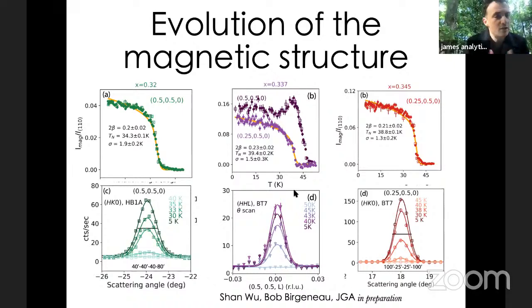And we've done some extensive DFT calculations with Jeff Neaton's group and Sophie Weber, where we showed that the stripe order and the zigzag order are actually very, very close in energy. And in fact, it's only a difference in the next nearest neighbor interaction that actually allows the system to switch from having stripe order as the preferred state to having zigzag order as the preferred state. So we think that's probably a natural explanation for why the switching turns off for the stoichiometric compound, and also why it has the opposite signs for the endpoints, for the underintercalated and the overintercalated. What's still remaining is the microscopics, of course, like how the spin polarized current couples to these magnetic orders, again emphasizing the moment is actually interplane. So again, how it couples to this Landau-Lifshitz-Gilbert equation is still perhaps not completely transparent.